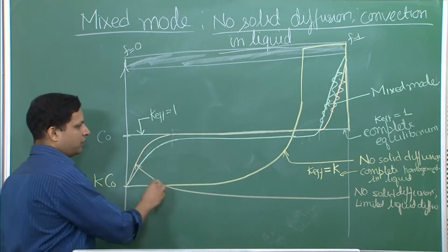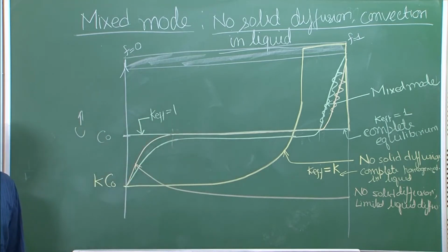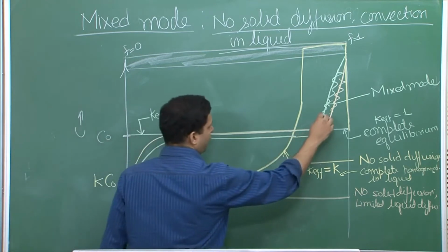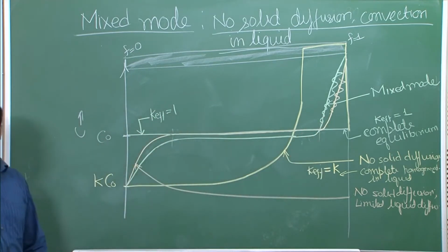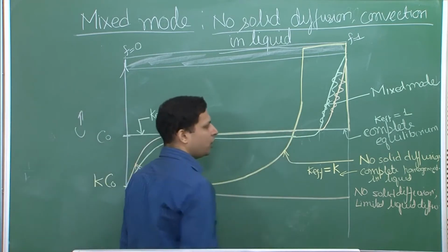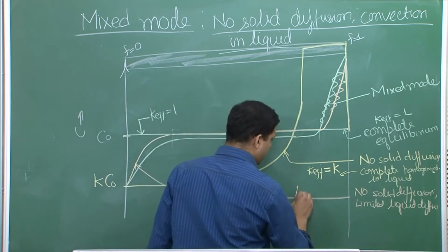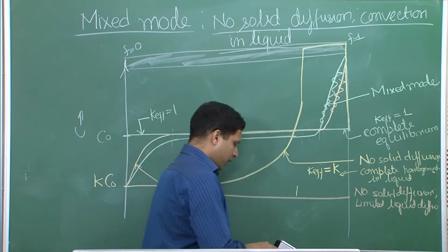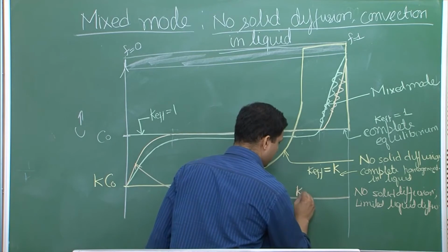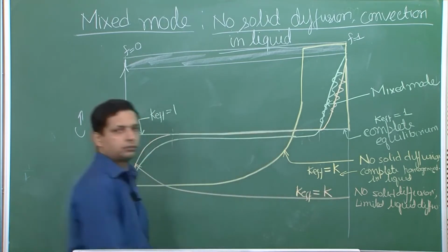Now in the next condition, which is no solid diffusion but with limited diffusion in the liquid, if you are looking only at the steady state, then the overall concentration is still equal to that of C0, or the alloy composition. Therefore for this also we can say that K effective is equal to K.